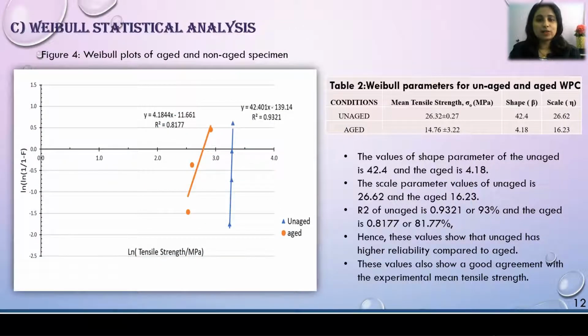Lastly is the Weibull statistical analysis. This graph shows the Weibull plots of the aged and non-aged specimen. From this graph, it is shown that the shape parameter or Weibull modulus of unaged is higher, which is 42.4, than the aged, which is 4.18, whereas the scale parameter of aged is 16.23 and non-aged is 26.62.